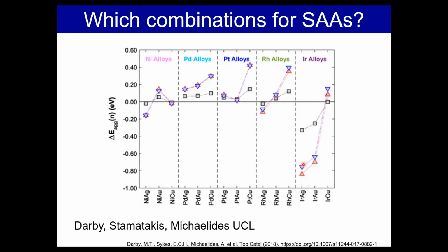In terms of stability, we've seen other people in the field run these catalysts up to over 500 Celsius, and they're still atomically dispersed. The only stability issue we have right now is just sintering of the host metal itself. For example, copper and silver and gold are very liable to sintering. So the activity shuts down, not when the single atoms disappear, they're always there due to thermodynamics, it's when the particle sinters and loses surface area. So that's why we're looking into things like atomic layer deposition to stabilize the host metal itself and then keep this chemistry even hotter in temperature.